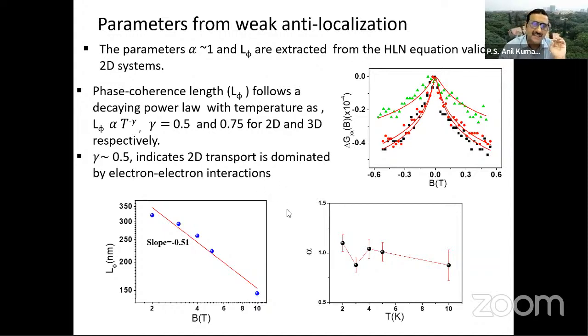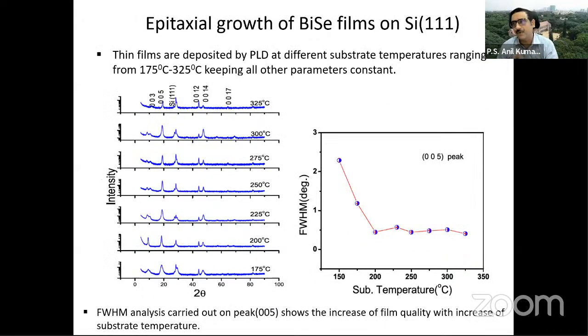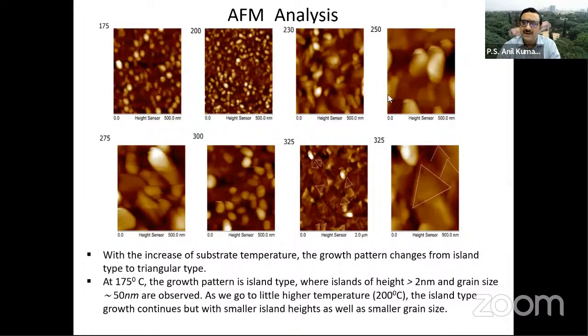Then we started asking the question: apart from the single crystal, can we also grow epitaxial films of this kind of material? So we use pulsed laser deposition to deposit BiSe films on silicon 111 substrate. You can vary different parameters in the laser. I'm just telling you one set of parameters that we varied, which is the temperature of the substrate. You grow the films at different substrate temperatures, and finally around this temperature, we get approximately good quality films. We also do atomic force microscopy analysis to assess the quality of the film, and this correlates with the other properties we are getting, which I'm not going to discuss here.